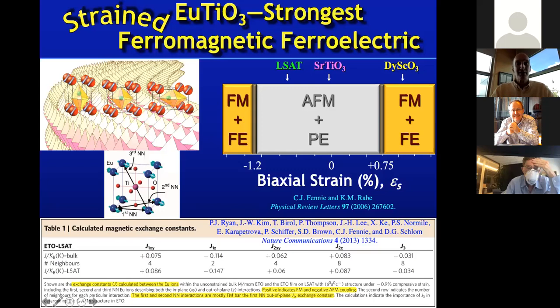If one looks at the second nearest neighbor interaction, which I should point out is super exchange through an intervening oxygen, there are second nearest neighbors both in the plane as well as diagonal here. One of them is ferromagnetic, and the other one is antiferromagnetic. And also there's the third nearest neighbor interaction. The third nearest neighbor interaction is also super exchange, through the intervening titanium, which I mentioned is in the center of this. It's a cubic perovskite, so the titanium is in the center of this cage. And so that gives rise to this third nearest neighbor exchange interaction. And you can see that there are 8 of them along the body diagonals,